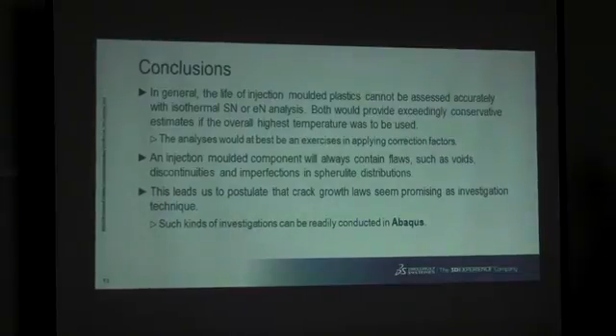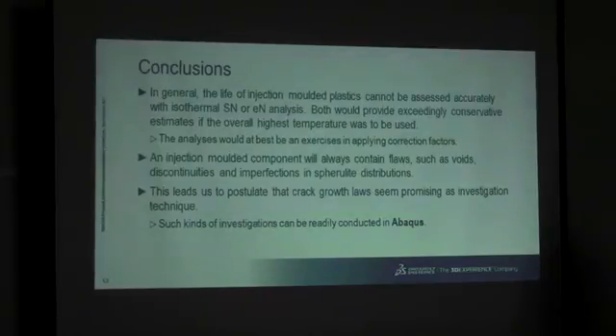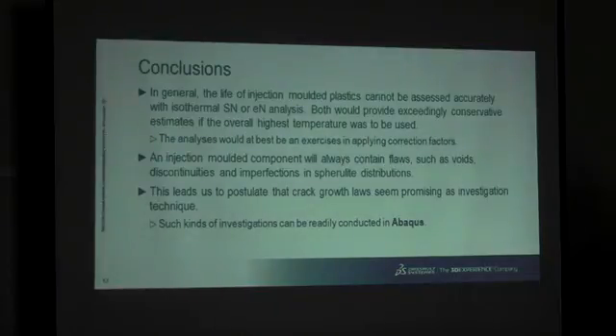So in general, what we found in this case was that the life of injection molded plastics can't be successfully analyzed using neither EN nor SN. It's not possible. We see an opportunity in fracture mechanics thanks to all the geometrical functionalities and, well, going back to the morphological structure, that there are individual entities that we can isolate and investigate. That's one of the benefits of polymer physics. You can actually create these structures in a unified environment.